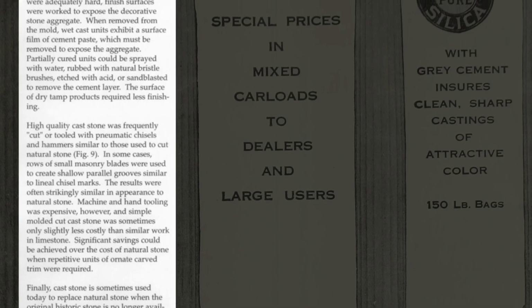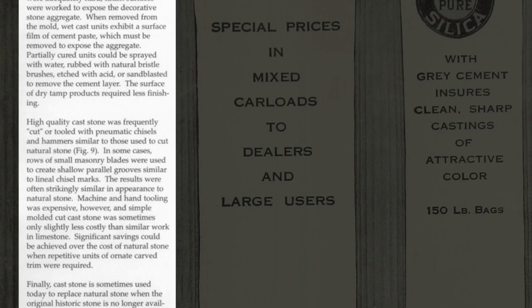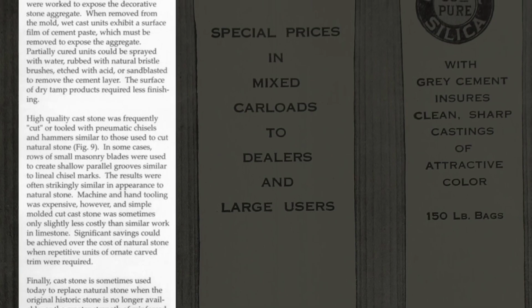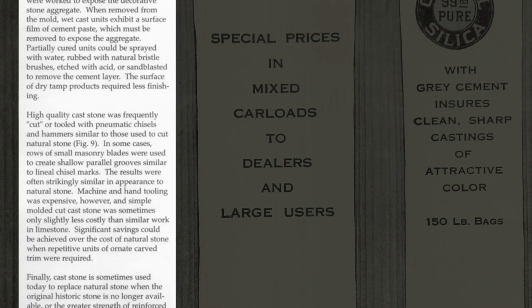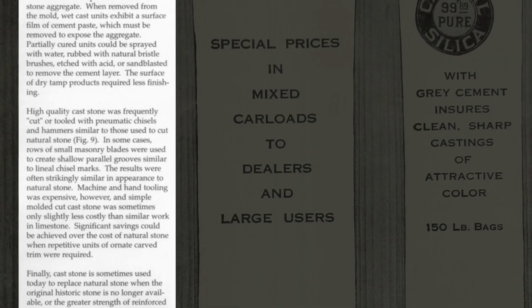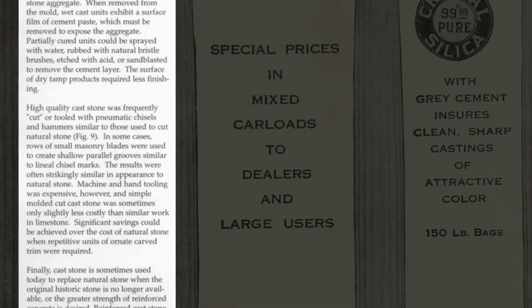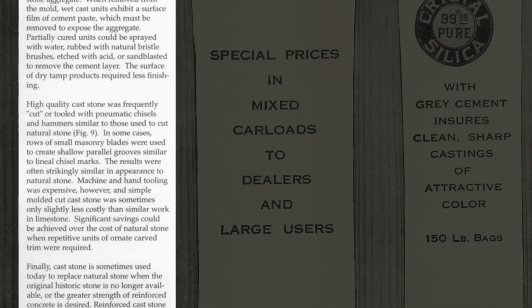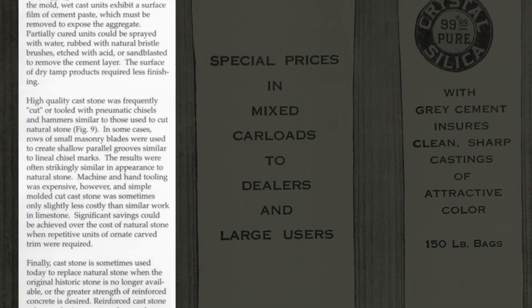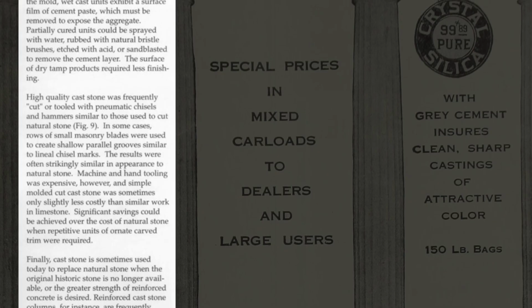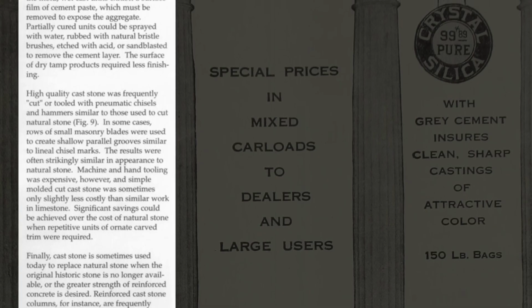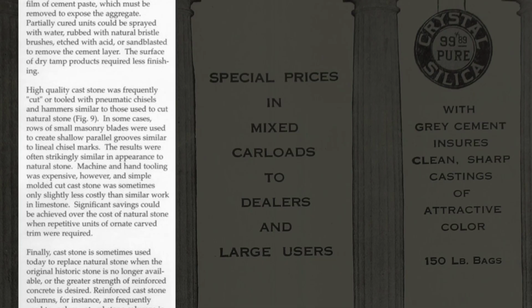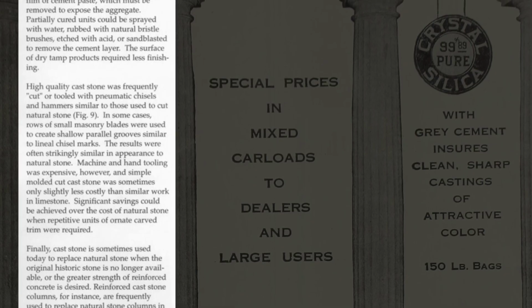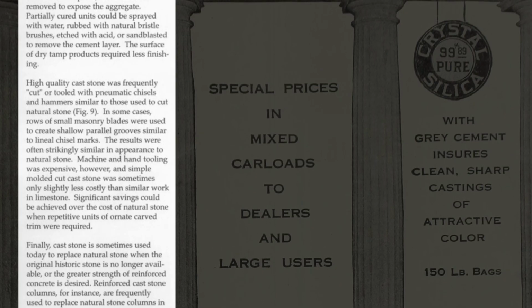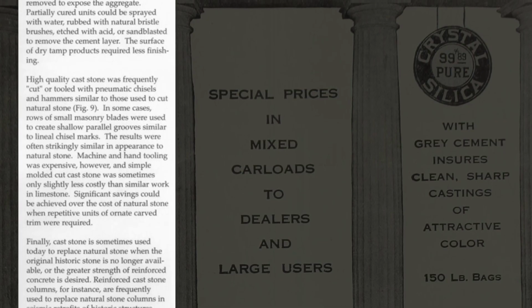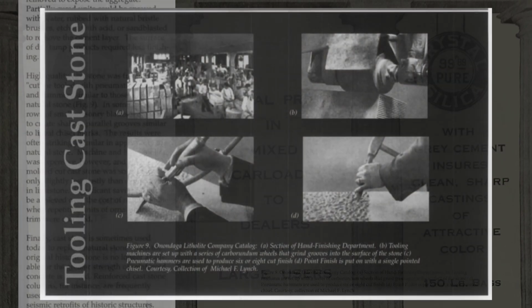When removed from the mold, wet cast units exhibit a surface film of cement paste, which must be removed to expose the aggregate. Partially cured units could be sprayed with water, rubbed with natural bristle brushes, etched with acid, or sandblasted to remove the cement layer. The surface of dry tamp products required less finishing. High-quality cast stone was frequently cut or tooled with pneumatic chisels and hammers, similar to those used to cut natural stone. And so here we have figure 9, reading as follows.